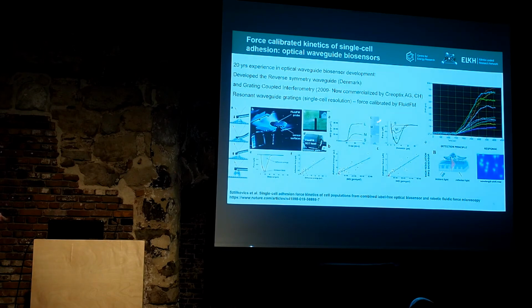So this is an example of a large cell. You can see that the optical signal is quite strong. And this is the force distance curve when this large cell was removed from the surface. This is the curve for a small cell. Basically, using this technique, we could calibrate the optical biosensor, and we could prove that there is a very nice linear trend between the optical signal and the actual single cell adhesion force.